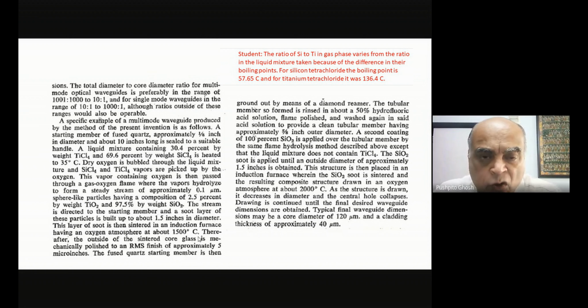So they're sintering, and all of these islands of glass, that soot, is collapsing into a coherent kind of a piece of glass or a film of glass. Thereafter, the outside of the sintered core glass is mechanically polished to an RMS finish of approximately 5 microinches. So after I've done the sintering, they're polishing the outside of the tube, and just getting a very mechanically smooth kind of a surface. Now, we'll see, it will be interesting. The fused quartz starting member is then ground out by means of a diamond reamer.